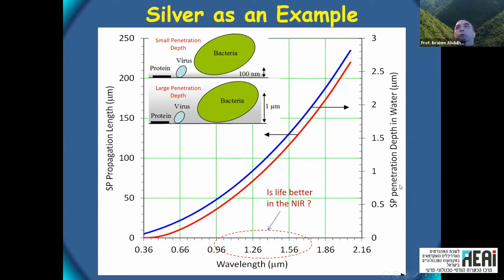However, for plasmonic sensing, we need to control the penetration depth mainly, because if we have a variety of bioentities, both molecules and cells, we need to be able to measure all of them. And as we see here, if we increase the wavelength, then the penetration depth increases more than linearly. That's because of the dispersion of the refractive index of the metal. If we work in the near IR, it becomes like 1 to 2 microns, which can be good for cells, for bacteria, for example. While when we work in the visible range, it's less than half a micron, so it could be problematic for detecting bacteria.